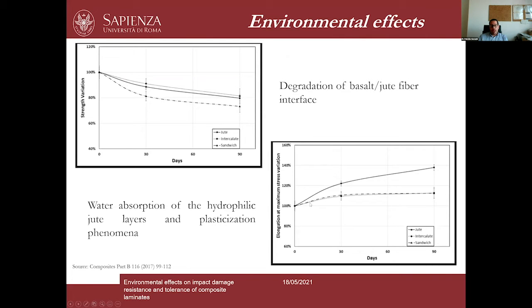And of course, the same degradation occurred for the strength, but a point of significant interest is the fact that, due to the moisture absorption, which is related, I would say, to the jute fibers, the composite material became much more compliant. This is also pretty evident here in this picture, where the elongation at maximum stress actually increased with increasing aging time.